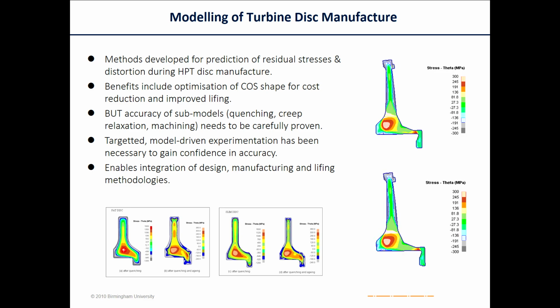So you can see here we were concerned with attempting to understand how that residual stress field is redistributed as the material is chipped away. And the reason why that's important is that those residual stress fields have to be accounted for in the lifing process for these components. They have to be taken account of in the estimate of the safe working life of the component. So precisely how we machine away the material becomes very important on the factory floor.